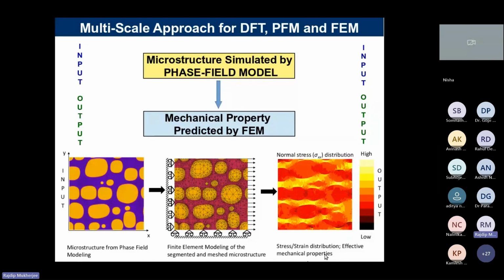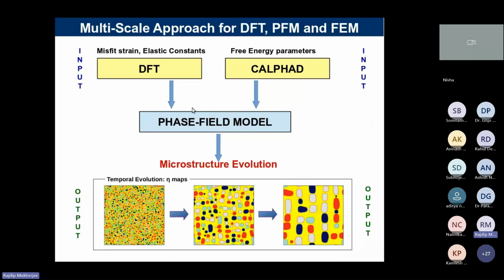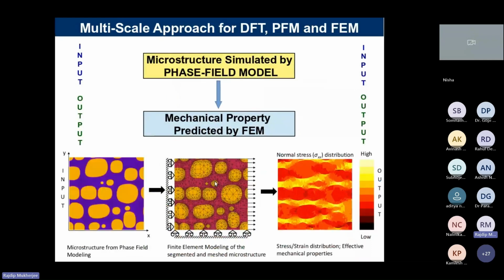So this is mostly the background for our software. We use the CALPHAD approach and density functional theory, and their output works as input for a phase field model. And then we use this phase field model for microstructure evolution. So in our software, you will mostly see this phase field model and this microstructure evolution in the m2mech software, right? And it can be integrated with the CALPHAD data. We will also show how it is integrated with the CALPHAD data. And these elastic constants will be an input. And once this is done, in the second demonstration you will see how you can predict the mechanical property once you have the microstructure.